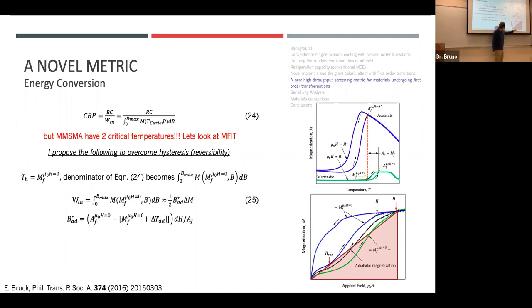I wouldn't discount it, because we have a little bit of an over approximation here. We're trying to predict the energy, the area under the dash-dot curve. We have under approximation and over approximation. It's pretty close. I haven't done an error analysis on it, but if we assume that the energy in is the size of this triangle, I can define the applied magnetic field needed based off of the sensitivity of these temperatures to shift with magnetic field. So as I apply a field, those temperatures shift, and if I know that sensitivity, I can define how much field it would take to completely transform it based off of transformation temperatures and my Clausius-Clapeyron slope.